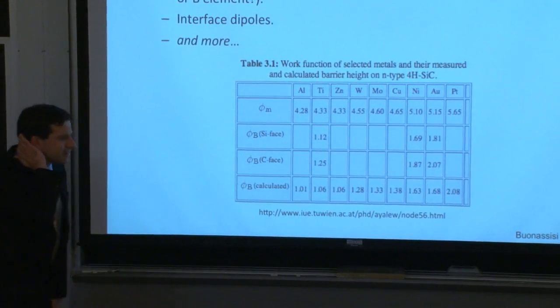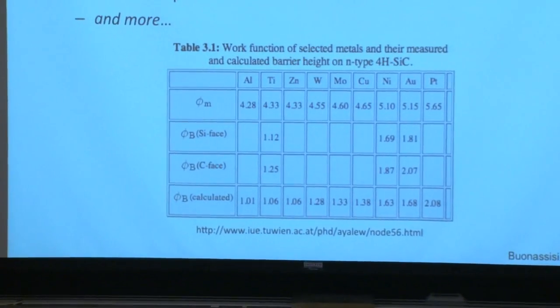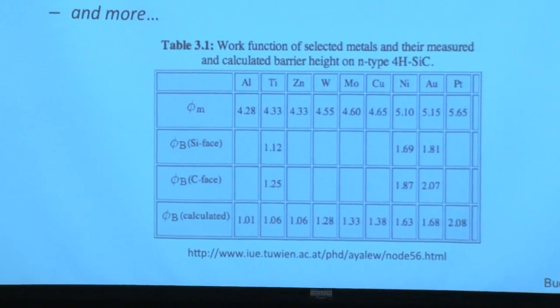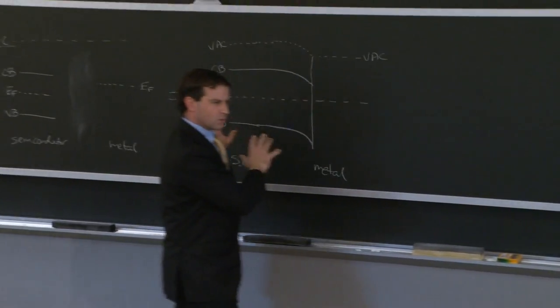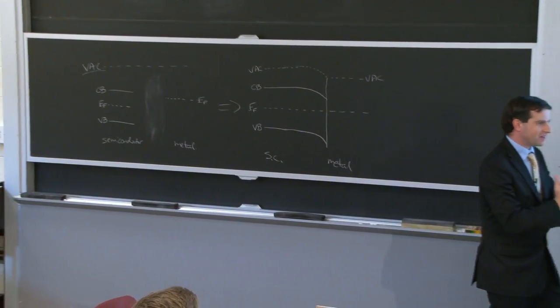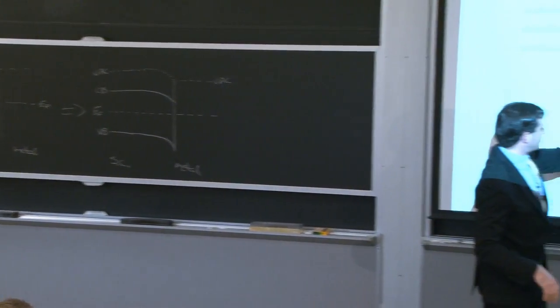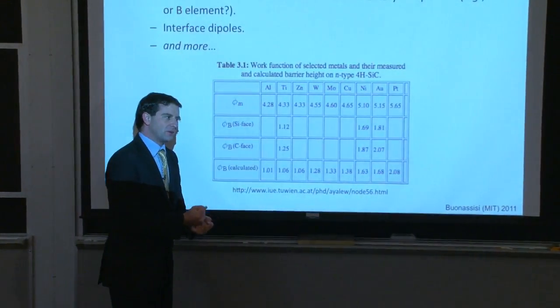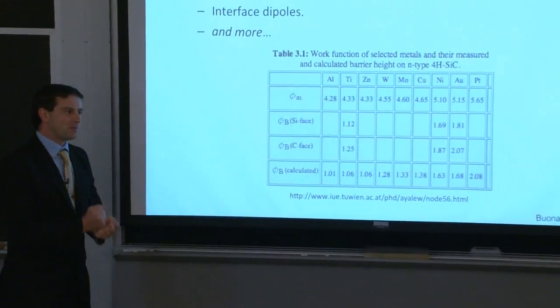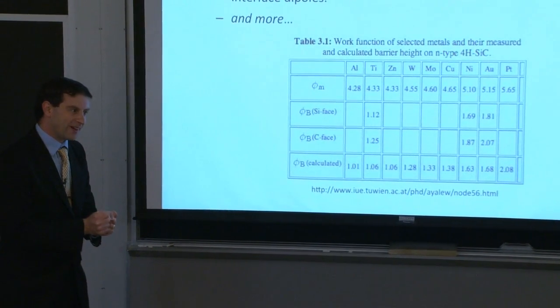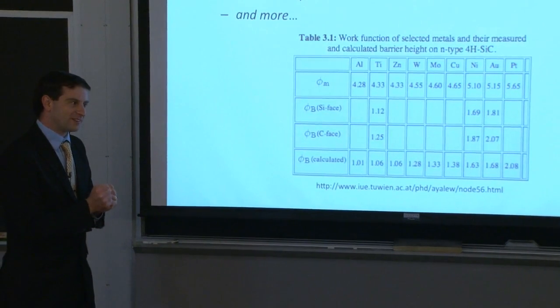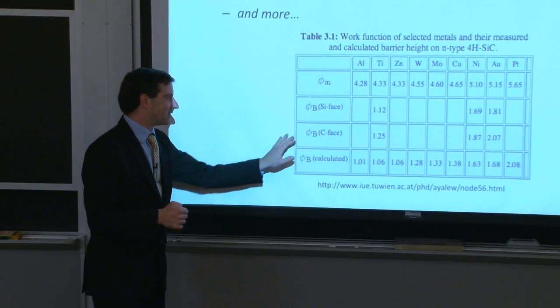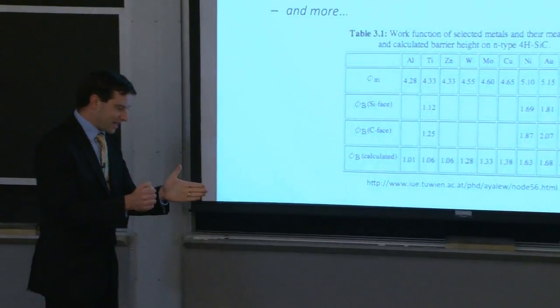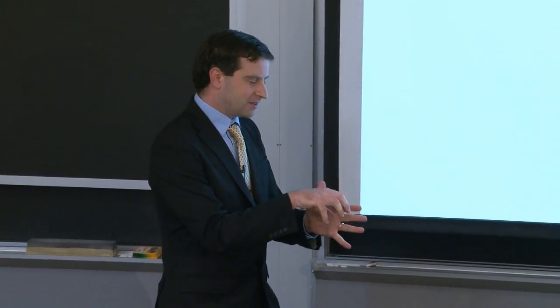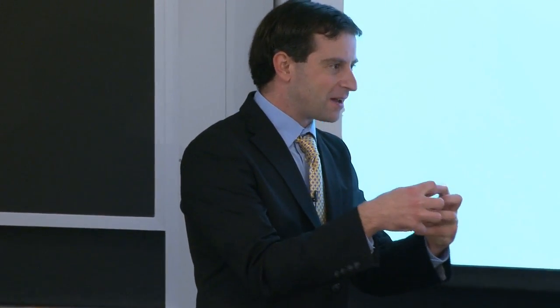So you glance at that, and you begin thinking to yourself, OK, this is macroscopic right here. This tells you from a continuum point of view what the interface should behave like, what the contact should be. But what I'm seeing right here from the data is that the atomic configuration at the interface really matters. So there must be something going on at an atomic level as well that's determining the barrier at that interface. In fact, there is: the dipole at the interface between the metal and that last layer of semiconductor. In other words, the distribution of charge between those two sets of atoms that are meeting at the interface determines in part the barrier height.